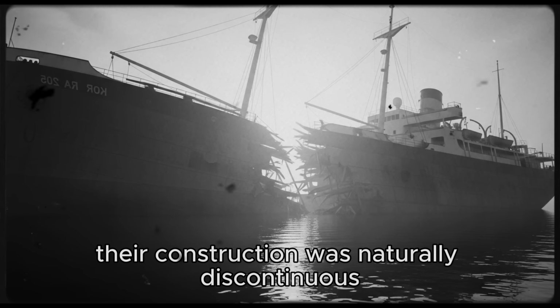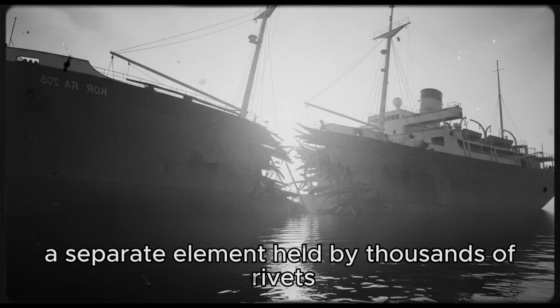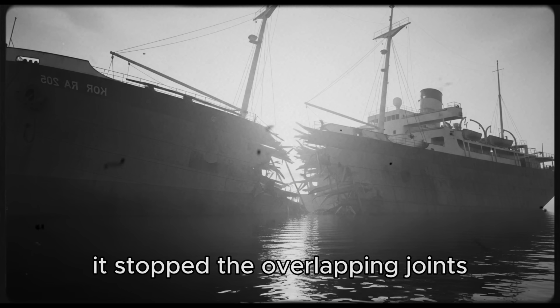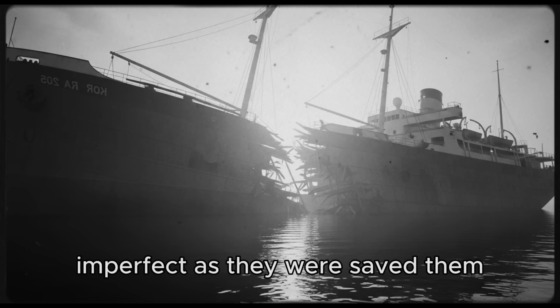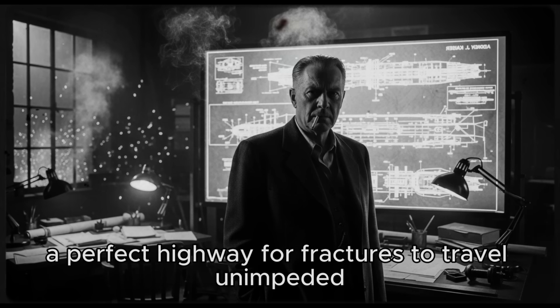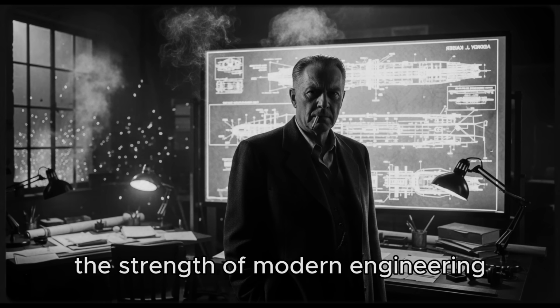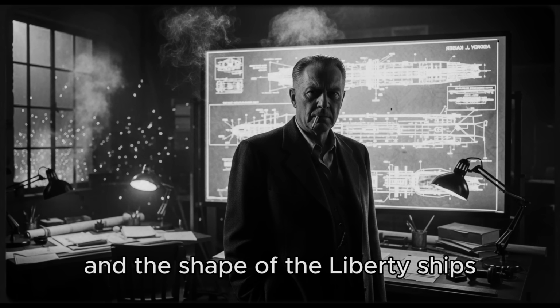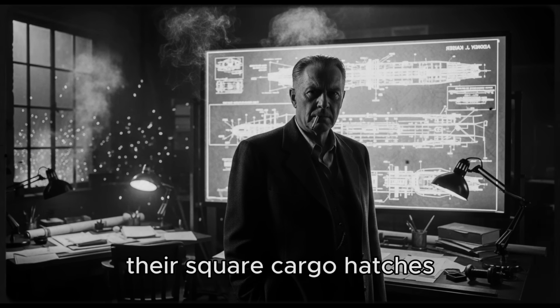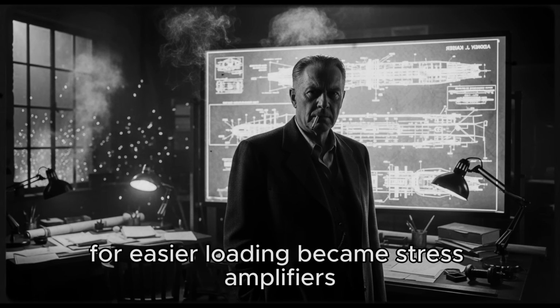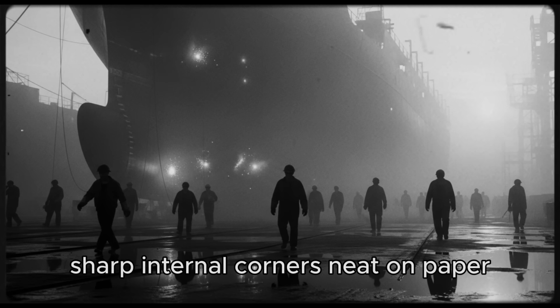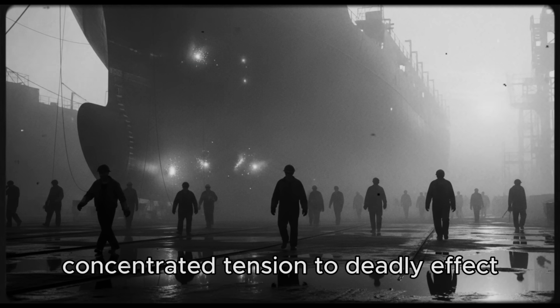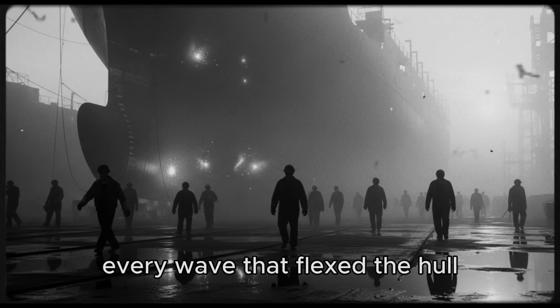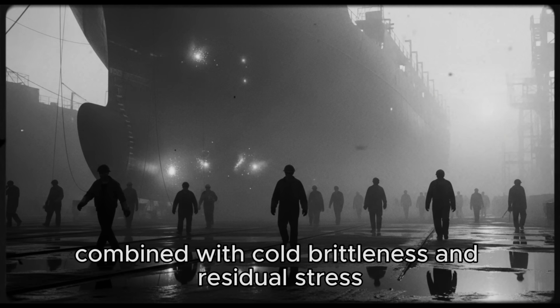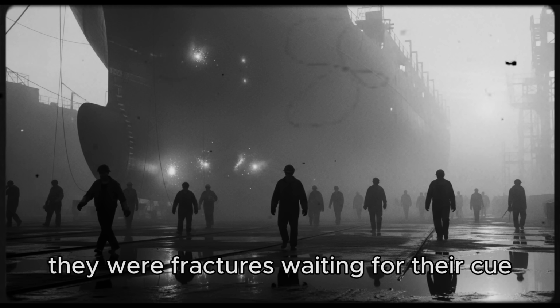Their construction was naturally discontinuous, each plate a separate element held by thousands of rivets. When a crack met a seam, it stopped. The overlapping joints, imperfect as they were, saved them. Welding, for all its efficiency, created continuity, a perfect highway for fractures to travel unimpeded from bow to stern. The strength of modern engineering had turned into its own undoing, and the shape of the Liberty ships only magnified the danger. Their square cargo hatches, specified by British naval architects for easier loading, became stress amplifiers. Sharp internal corners, neat on paper, lethal in practice, concentrated tension to deadly effect. Every wave that flexed the hull sent invisible tremors through those corners. Combined with cold brittleness and residual stress, they were fractures waiting for their cue.